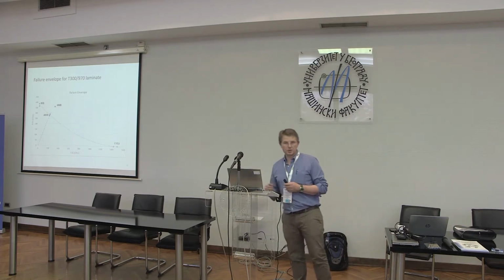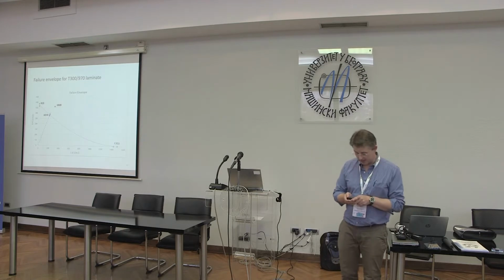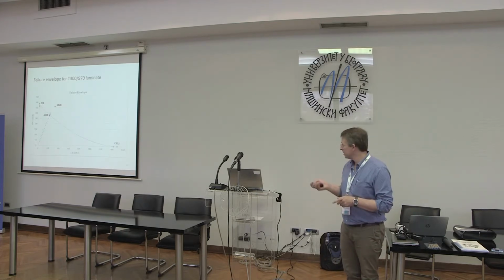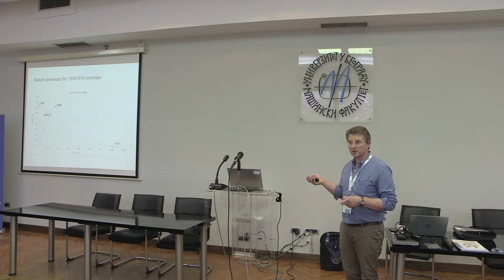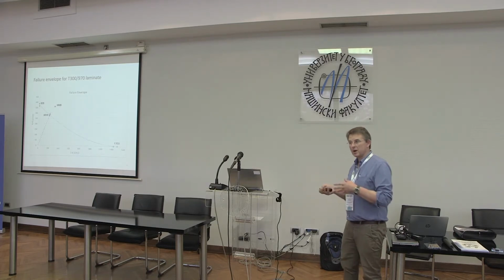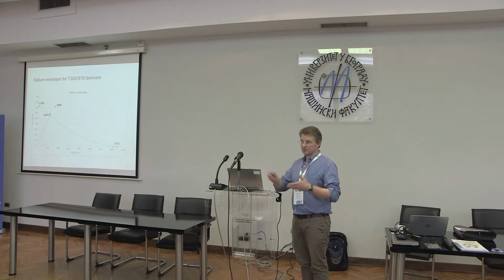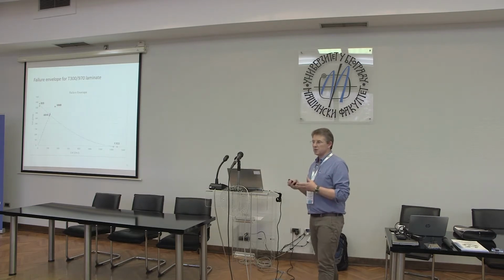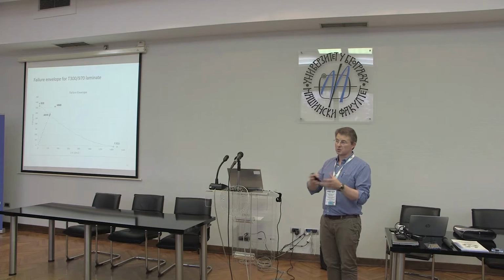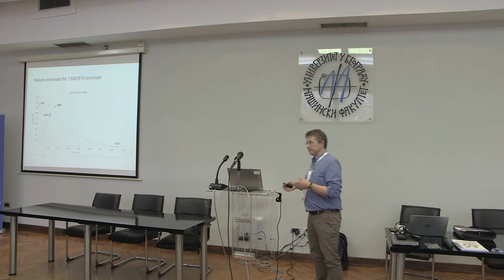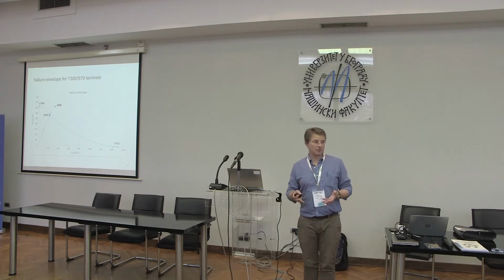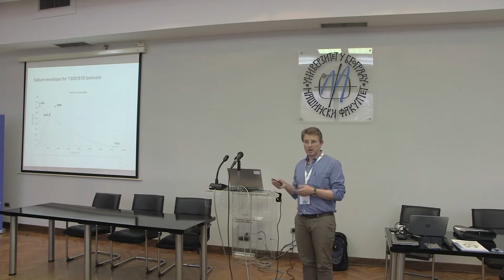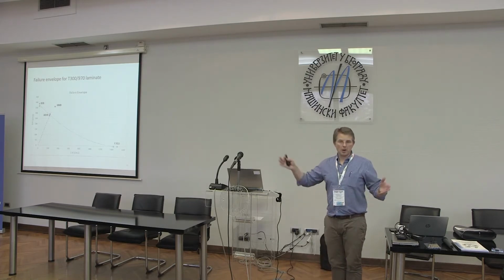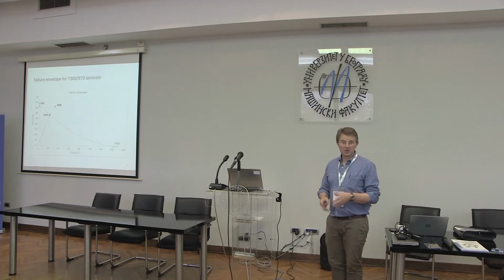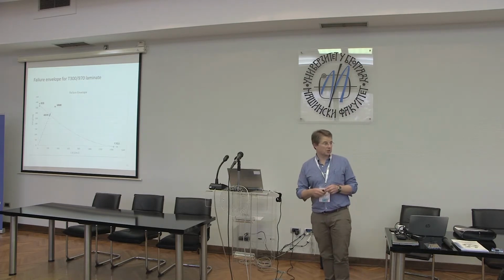And it's important to work it out for the very reason we see here, because we know that the mode 2 fracture resistance is so much higher than the mode 1 fracture resistance. So if we can't adequately partition a total energy release rate in a given system, we don't know what G values to ascribe to actually work out the toughness. So ultimately it just leads to a higher degree of conservative design. If we don't know, we have to say, well, let's assume it's all mode 1 and we work with a lower value. Okay, well that's not great if you're trying to minimize the weight of a structure